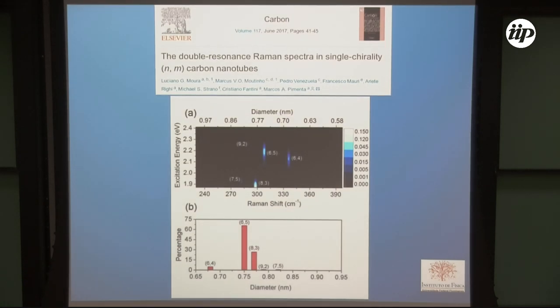Okay, another example. My time is running out. This is a very interesting paper. The experimental part was done mainly by Luciano Moura. At that time, he was a PhD student in Marcos Pimenta's group. Now he is a professor at Universidade Federal de Viçosa. So we had some carbon nanotubes with enriched chirality. They do some kind of process that can enrich and have basically some chirality. So here I have the Raman shift of the radial breathing mode, and if you compare with the excitation energy that happens here, you will see that there is a resonance when you change the laser light.